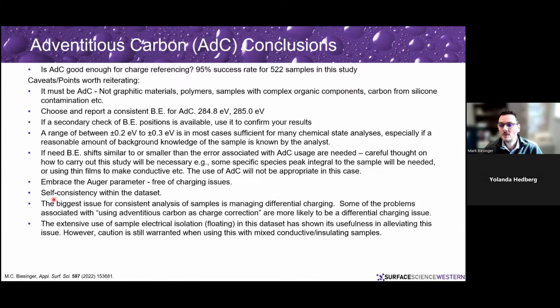We do need to choose and report a consistent binding energy for adventitious carbon. That's a problem in the literature. We can use secondary checks of binding energy positions to confirm your results, which is always a good idea. If you can confirm your results using other peaks, great. A range of plus or minus 0.2, 0.3 eV is generally sufficient for most chemical state analyses.